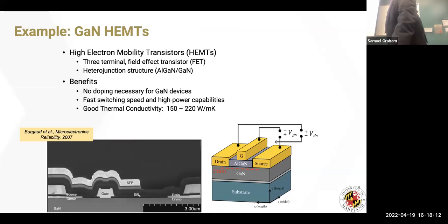And so just quickly, because of the time, what we're going to start out with are gallium nitride heterojunction or high electron mobility transistors. And so what you have here is a material where we're going to have a material like aluminum gallium nitride sitting on gallium nitride. This creates what's called a two-dimensional electron gas. This is basically a nice source of electrons that sit right there near that interface. I don't have to dope the material, this forms. And so this gives me my channel where current wants to flow.